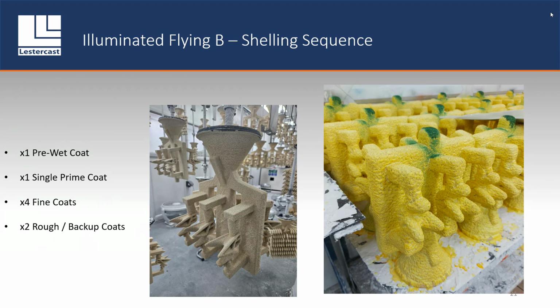Each part is different. I mean that in the sense that each different type of component is different. This particular Flying B here, in this configuration, has one single prime coat. That's the first coat that touches the metal. Behind that, we've got some fine coats, and then finally 2 rough coats or backup coats to give the shell the strength. If this was a different component, we'd have a different sequence. We'd always have a single prime coat or maybe a double prime coat, but we might play around with the other coats to get different shell strengths or profiles, depending on if we've got deep pockets, for instance, which might be quite difficult to dry, or if the shell is getting particularly thin, we might put an extra backup coat on. Over the time that we've been doing this, we found that this sequence works best. So it is a little bit trial and error.